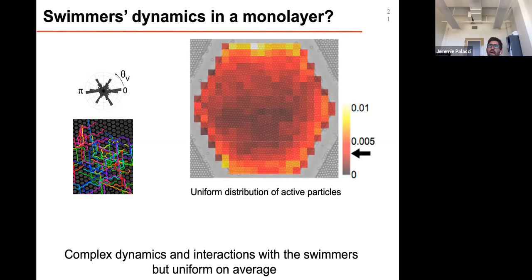On the other hand, if you look at the distribution of active particles in the system, what I want you to get from this figure is that it's fairly uniform. There's a tiny bit of accumulation of the active particles at the boundaries, but it's more or less very uniform. And that's very important for two reasons, because if on average the active particle spends the same amount of time everywhere in the monolayer, then we can step back and do a mean field approach where we don't look at each microswimmer individually, but we just consider them as a bath.